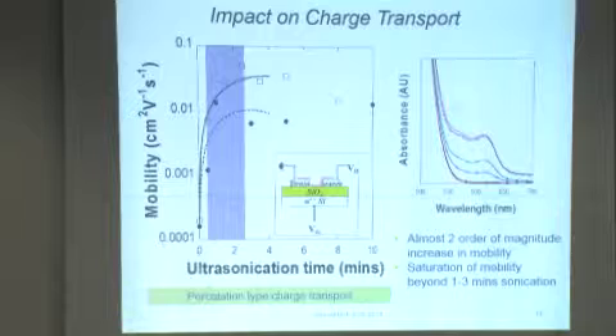All right, so we saw saturation. As a result of that, we started thinking about whether there may be a percolation type charge transport mechanism at play. And just to summarize a little bit, there was almost a 2 order of magnitude increase in mobility with ultrasonication time, and then again it saturated.